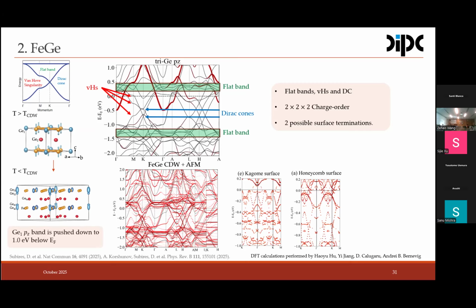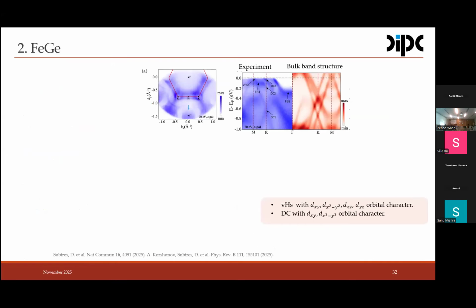Again, which is also a common feature in these Kagome materials, we encounter surface states, surface bands due to different surface terminations. So we mix and merge this charge density wave antiferromagnetic state and different surface terminations. We end up with a complete mess of band structure. So we put the sample on the ARPES beam. We can actually see the hexagonal Fermi surface typical of a Kagome material with pockets at the K point and some low intensity in the gamma prime due to the matrix elements in ARPES.